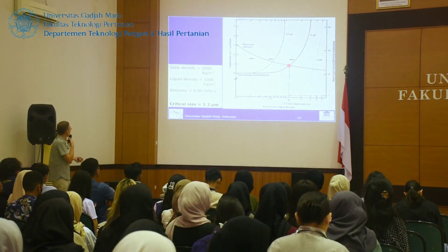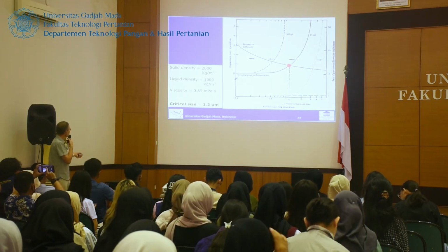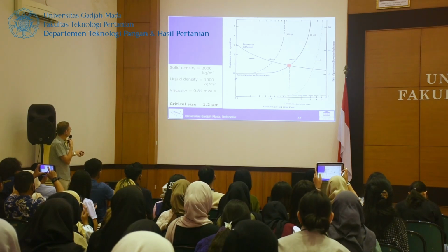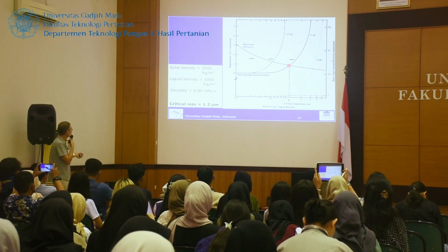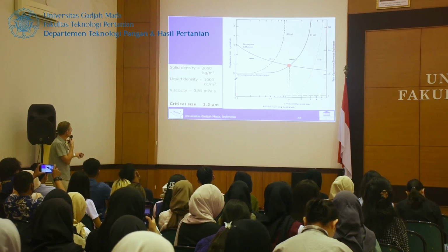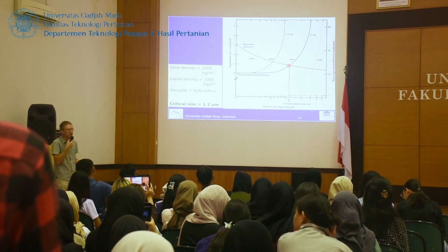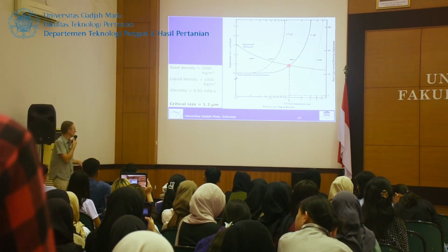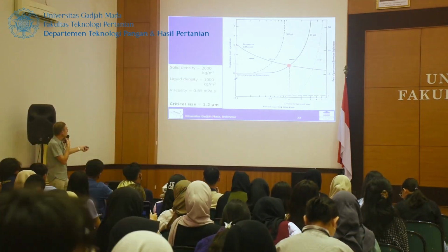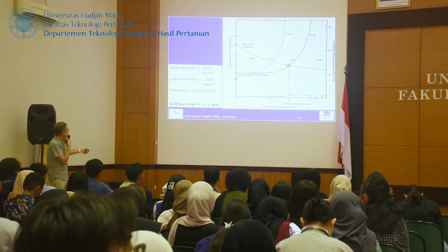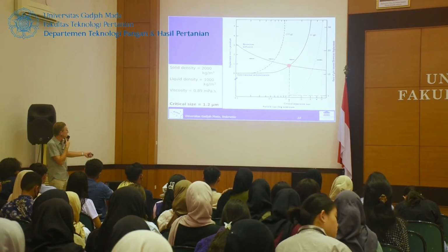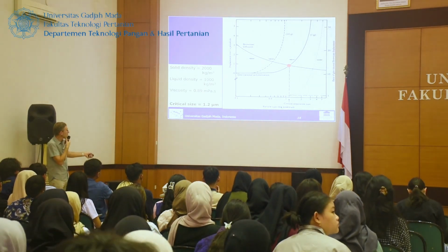Calculations were done for particles with a density of 2000 kilogram per cubic meter in water at room temperature, density of 1000 kilogram per cubic meter, with the viscosity of water at 20 degrees. It shows the distance that particles move over 1 second due to the gravity effect. And we have seen that the velocity there is increasing with particle size.